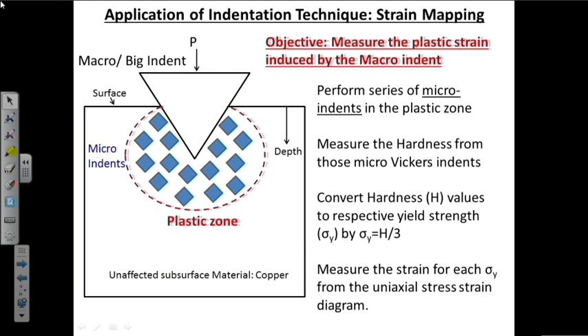Now, I would like to talk about some applications of the indentation technique. One of the applications is strain mapping in the subsurface of an indent. So, what we want to do? We want to measure the plastic strain induced by a macro indent. In this figure, this triangle shows a macro indent or big indent which is loaded by a force P onto the surface of a specimen, and when we apply a certain load, it creates enormous plastic deformation in the subsurface below the surface, which is shown as a dotted line, and this region is called plastic zone.